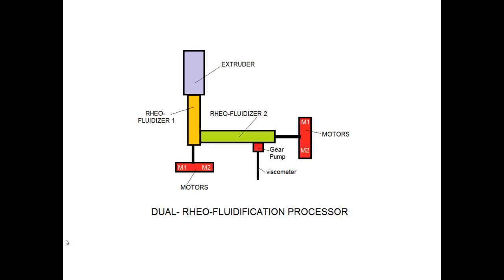by coupling two rheofluidizers, 1 and 2, here yellow and green, and I have done it in this particular configuration. So you will recognize the rheofluidizer 1 with extruder feed and the two motors M1 and M2. It has of course the ribs and so forth inside, the cone, the expansion of a melt. And instead of having an output to a pelletizing line or to viscosity, I'm using a second rheofluidizer, with its own motors, with its own temperature controls, and it has a gear pump in the back, the outlet, and a viscometer. Also coupled with that, but not shown, I can pelletize a melt while its viscosity is being measured in parallel.